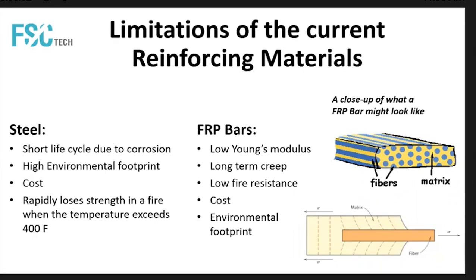That means that is the reason why you get shear and long-term creep, and because of this, increasing the section of a composite, you don't get very much increase of total strength. Basically, you drop the specific strength. Then they have a low fire resistance because obviously resin matrices burn at relatively low temperature. And when the matrix is gone, basically you have only the skin that is holding the load.